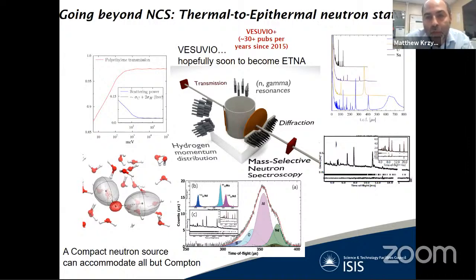So we have two techniques that actually can be used to globally fit the nuclear quantum properties in a system under investigation. A very good example of joint use of those techniques is the picture at the bottom of the slide that I'm showing, which is a high entropy alloy that has multiple recoil peaks that we can observe in neutron Compton scattering, but also some of them are quite overlapping. And if it wasn't for the fact that we can resolve neutron absorption resonances through gamma spectroscopy, we would have never been able to separate the nuclear quantum effects measured from heavy nuclei, in this case, molybdenum and neodymium. And jointly applying gamma and Compton spectroscopy, we can globally fit those zero point energies of all atoms present in this alloy, jointly performing neutron transmission and high resolution neutron diffraction on the sample.